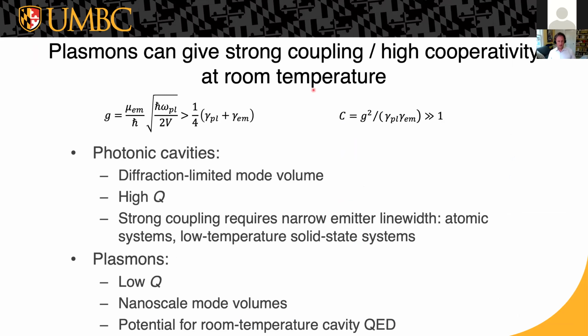But in both cases, what you need to do in order to get higher cooperativity or strong coupling is to have a coupling strength that's large compared to the line widths in the system, the cavity line width or plasmon line width and the emitter line width. And for photonic cavities, the coupling strength is strictly limited by the diffraction limit. The coupling strength scales inversely with the square root of the volume. So the smallest mode volume that you can get is limited by diffraction. So the only thing that you can do further to get strong coupling is to make the line widths of the system narrow. Making the cavity line width narrow is not a problem.